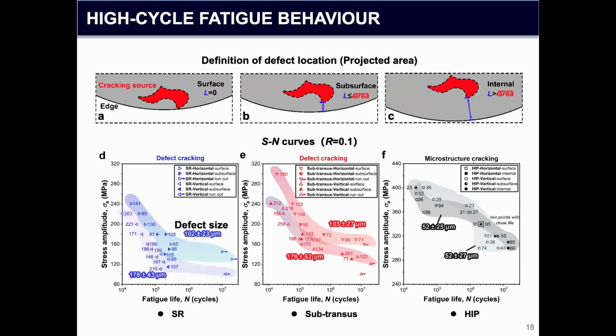So these are the results of the high cycle fatigue data, and we can find that for a given stress amplitude, the sub-transus gives a higher fatigue life, and the HIP one is the best, because the fatigue strength has been raised from about 120 megapascal to more than 280 megapascal.